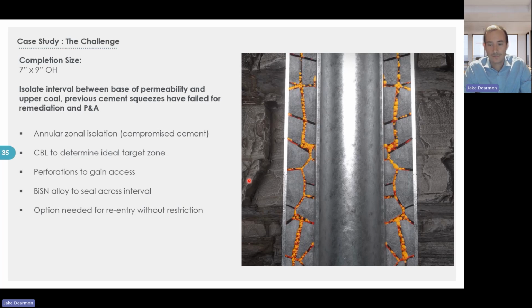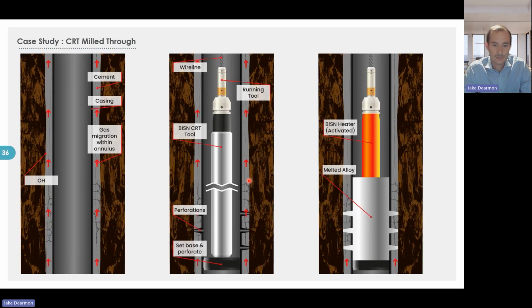One of the unique things about this campaign is it was a mixture of wells where some actually needed the option for re-entry, whether that's we want zonal isolation and we want to go recomplete the well or reperf a well at a deeper depth, or such as a CCS example where we need to seal everything above that zone, but we need access below afterwards. So what we're able to do in this situation is go in and actually perforate. We set a base for the perforations, whether that's a cast iron bridge plug or cement top. Most of these wells, we actually use top of cement that was already inside the production casing there. We go in and set a bismuth plug on E-line, which allows that alloy to actually flow into those perforations.